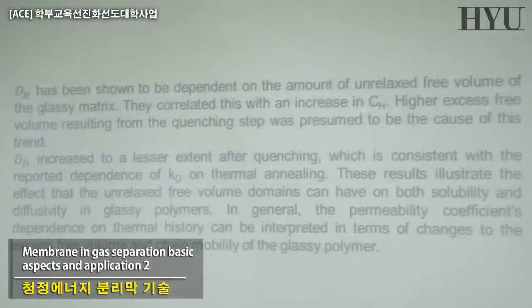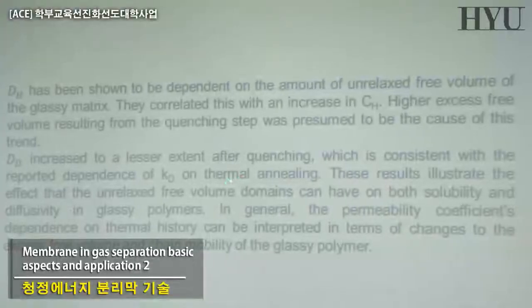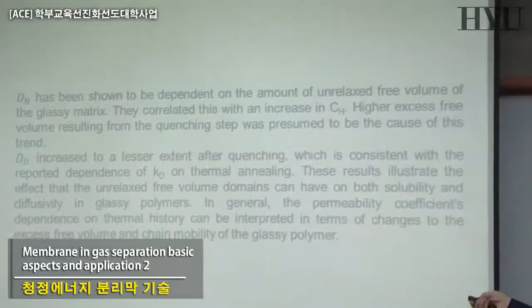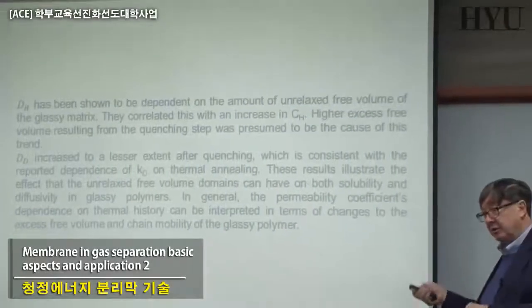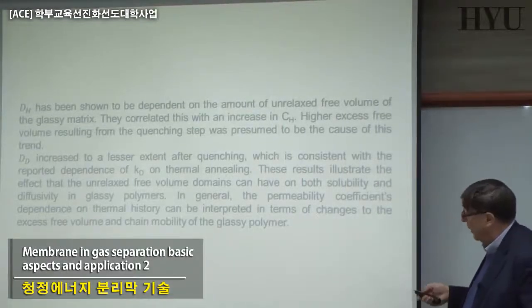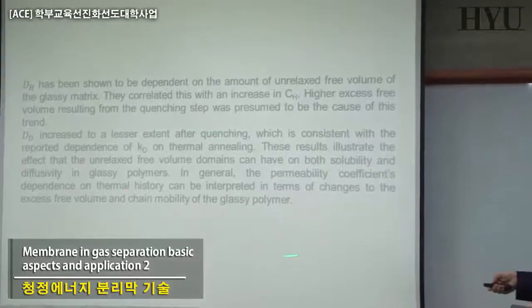This is thermal annealing much more soft, to 80 degrees, 100 degrees, that always is present. But already it was possible to find a relationship between this thermal treatment and the change of the diffusion coefficient and of the specific interaction defined by the KD, etc. That's why I'm suggesting to use more and more these.